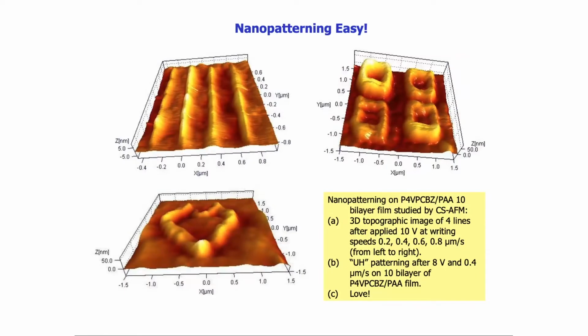What we simply do is we move the conducting AFM tip, and wherever it moves, it electropolymerizes the film. So we were able to make different line patterns, different shapes, different heights based on changing the bias voltage or changing the number of layers or changing the